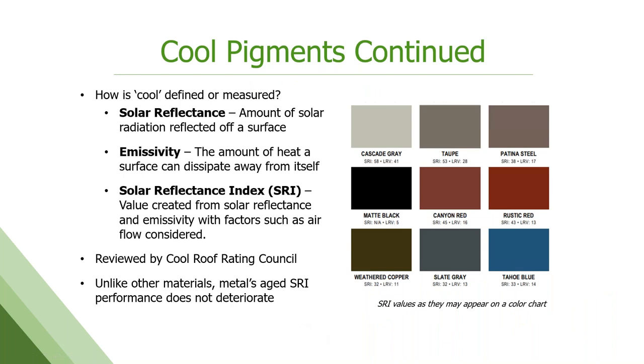But there's some terminology here that gets people a little hung up sometimes. So what is cool? Well, we measure it in three different ways. There's a solar reflectance value, the amount of solar radiation that's reflected off the surface. There's emissivity, which is the amount of heat a surface can dissipate away from itself after it gets hot. You take those two values into a very long, nasty mathematical calculation, and you end up with solar reflective index, which is what LEED and other building codes and bodies are using now to define cool. That's the SRI value. The higher, the better, typically. Cool Roof Rating Council is the third party that keeps everyone honest on that, and you can rate and list your products. And then there's the aged value.